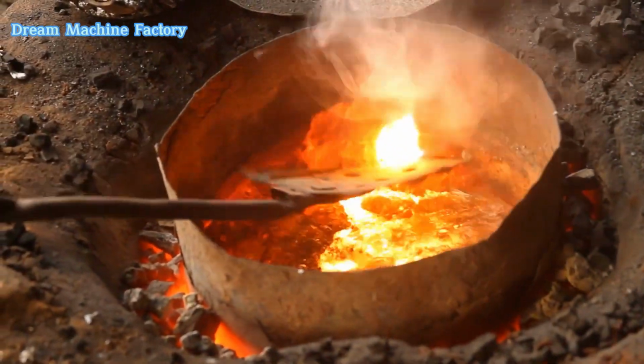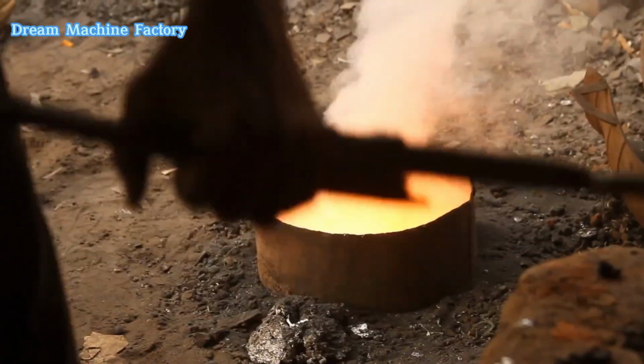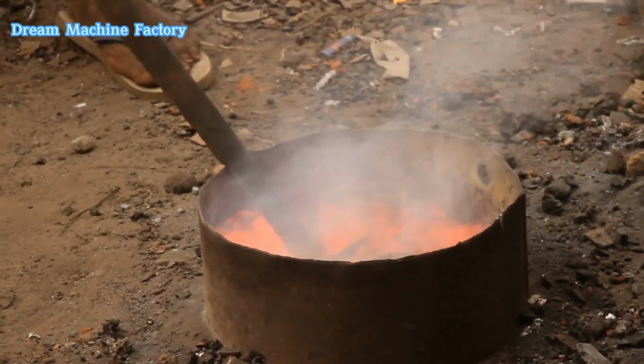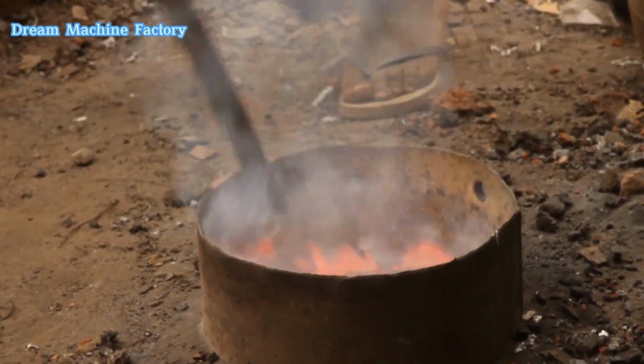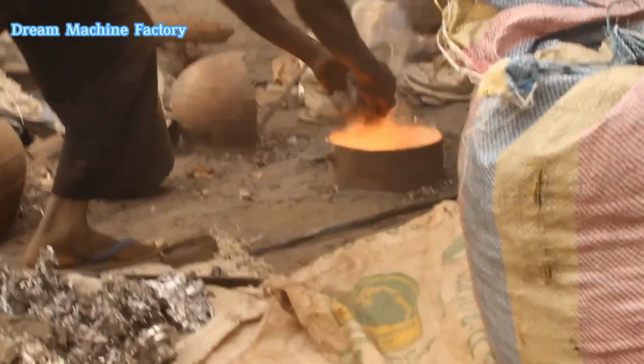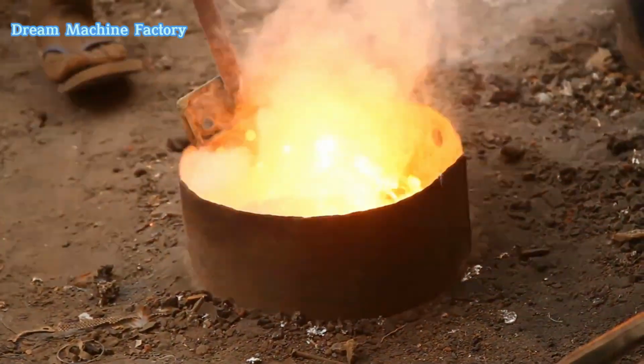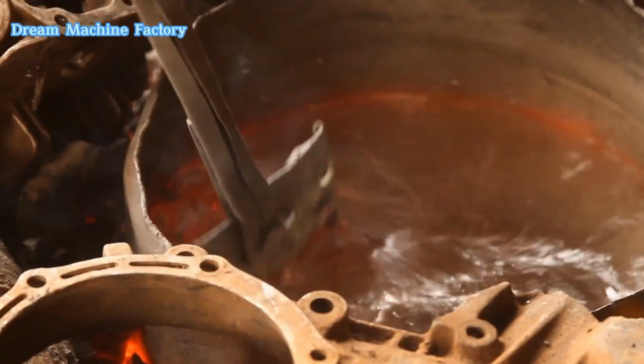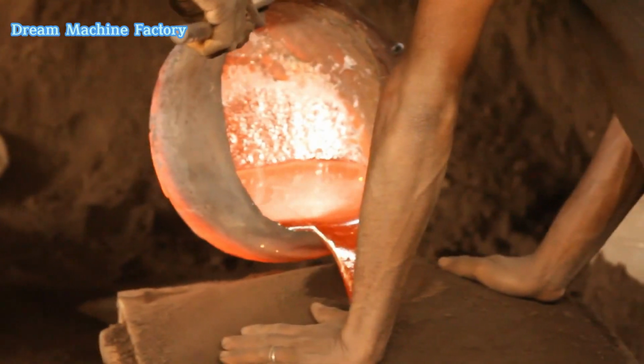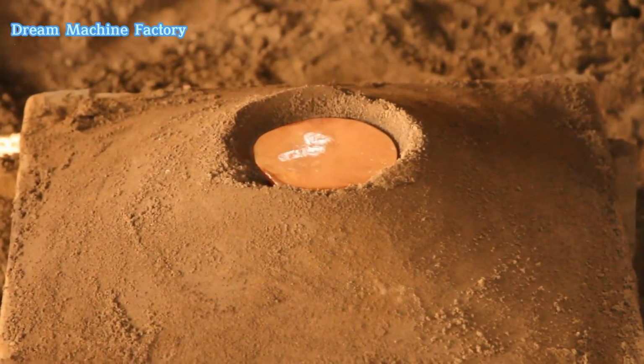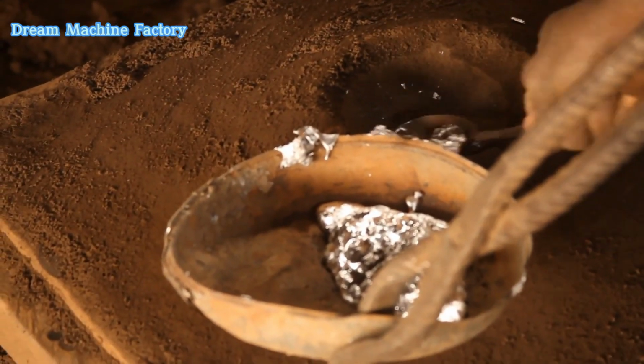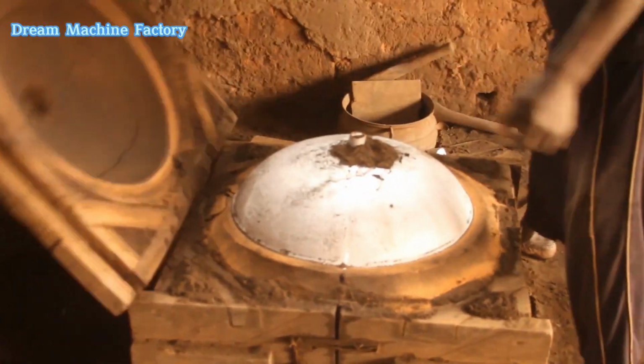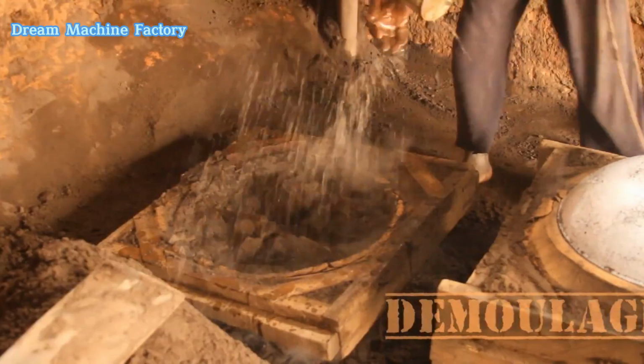To ensure a clean melt, artisans use improvised tools to skim off impurities and dross, oxidized metal, that rise to the surface. Once fully liquefied, the molten aluminum is carefully poured into the prepared mold, marking the next stage of the pot-making process. Artisans carefully lift the crucible using tongs and pour the molten metal into the mold through the sprue entry channel. This process requires precision to ensure a smooth fill without air pockets. The metal flows into every cavity, shaping the final pot structure.